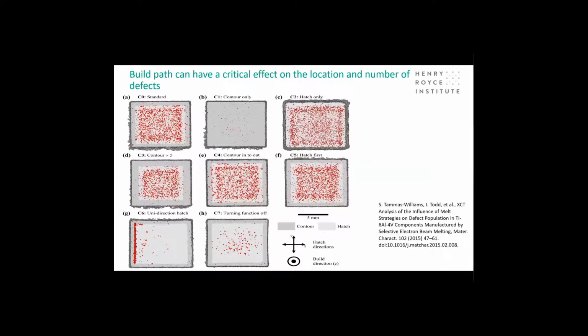So let's assume that you have your material and your CT scanner set up appropriately, and you can clearly see from these different scans that the build path and the build conditions can have a very critical effect on the distribution, location and size of the defect population. And it is possible, by controlling those scanning parameters, to ensure that the worst defects occur in the regions where it is least likely to have a deleterious effect on the fatigue life.